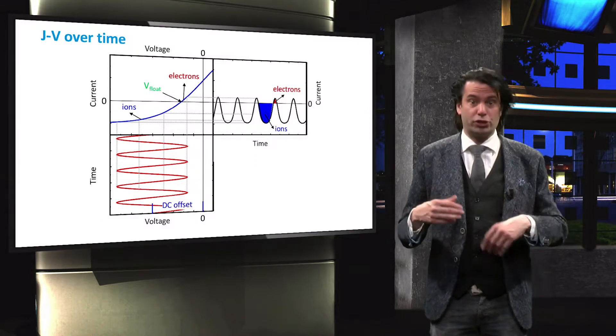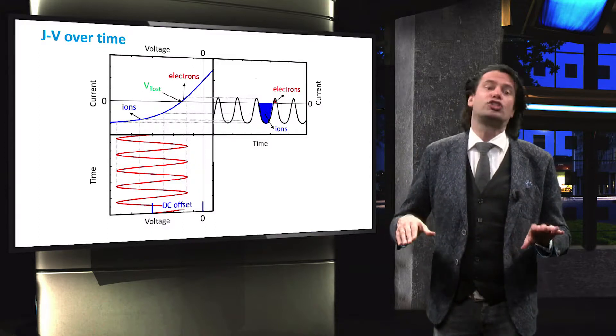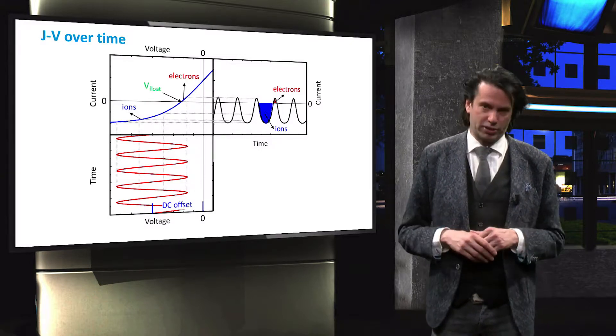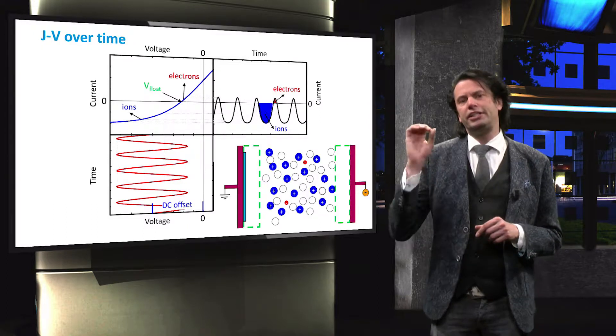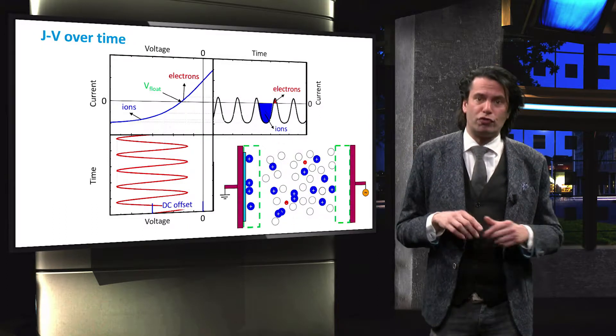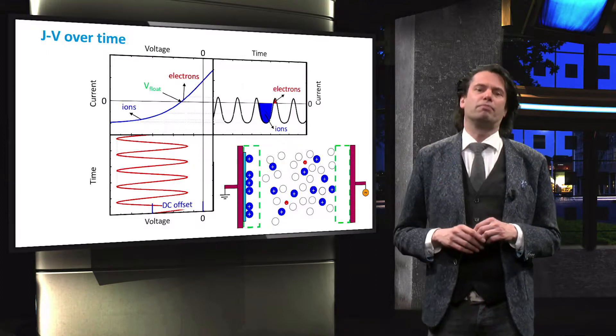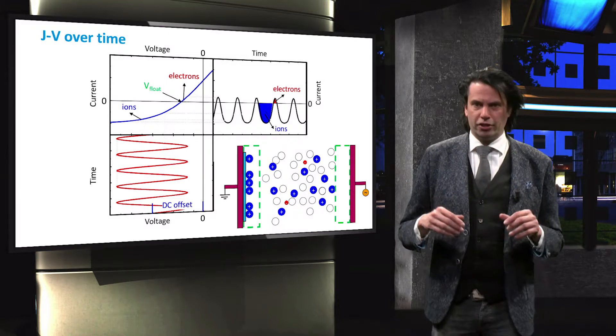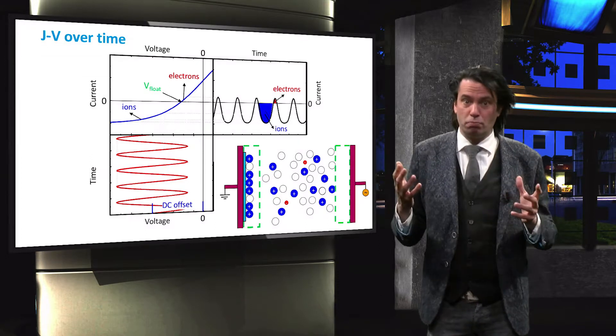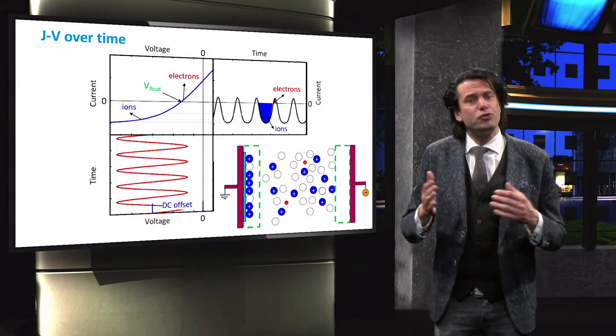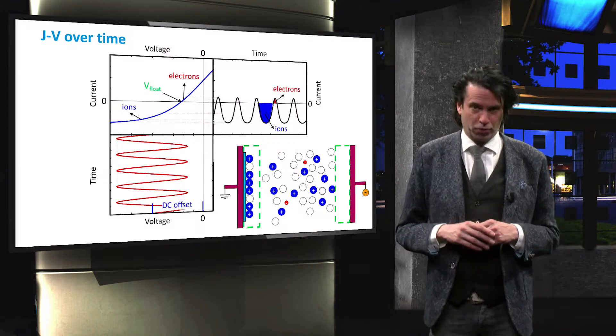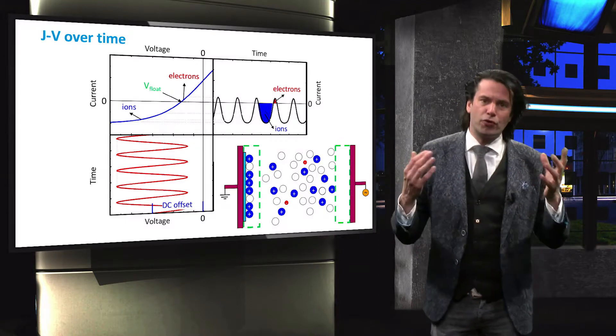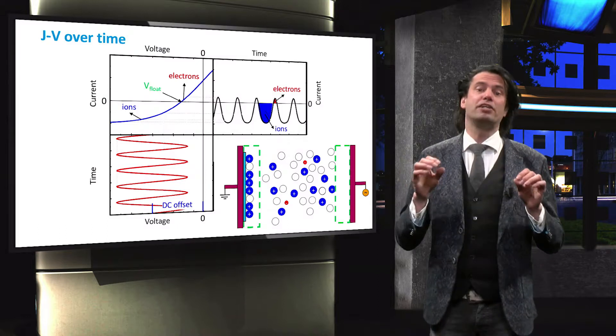The grounded electrode, at which the substrate is generally located, undergoes the same cycles of ion and electron bombardment, only at a one-pi phase shift with respect to the powered electrode. The adsorption of ions impacting onto the surface of the substrate leads to the growth of a thin film. The ions are not the only species responsible for film growth; reactive radicals created in the plasma zone, which are neutrally charged, can diffuse to the electrodes where they stick and contribute to film growth.